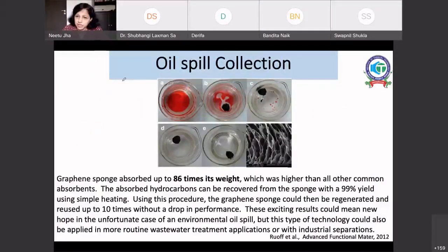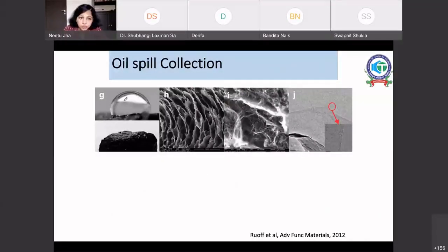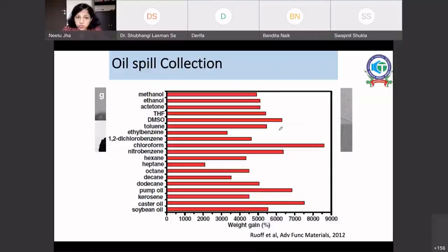And a similar study was done earlier by Ruoff and his group, where graphene aerogel was prepared. Aerogel is a highly porous structure. See, so all these things are pores. It is very lightweight. It can float on the water surface, and it does absorb all these oils in the pores. And then you can remove these. So this is hydrophobic, and you can remove these oils later and use them. So many different types of materials or solutions were absorbed in graphene aerogel, and the weight gain was much higher. So chloroform, nitrobenzene, hexane, heptane, octane, decane, kerosene oil, pump oil, soybean oil. So many different oils were studied.